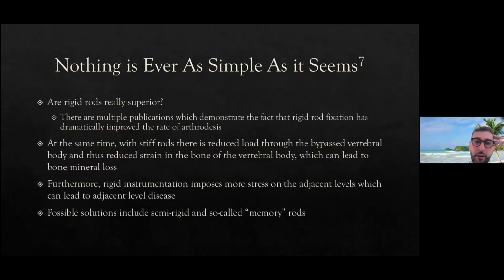So this is a review of the literature that I've put here. And basically the premise here is, the question is, are rigid rods really superior? And there's multiple studies which demonstrate the fact that rigid rod fixation has improved rate of arthrodesis. Now, those studies are not referring to the relative rigidity. They're just saying putting rods and screws versus onlay fusion. But there are also studies that show a higher rate of fusion, and I'll show you a couple with rigid rods. But at the same time, there's problems with these stiff rods.